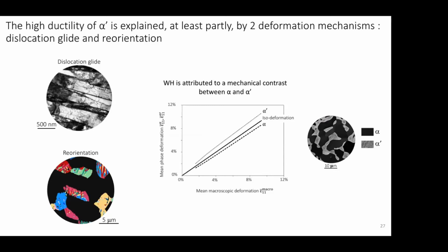But we have to keep in mind that it's quite complicated because, I didn't show it here, we know that reorientation starts at the beginning of plastic deformation, but it's in the same region where the dislocation glide will start. We also know that it depends on the texture of the parent beta phase; not all the martensite will bring reorientation. So we have all of that in mind, and it works all together. We also have the mechanical contrast between alpha and alpha prime. And we think that because of all that, the reorientation will be harder and harder to induce. And maybe we also have some work hardening thanks to that effect.